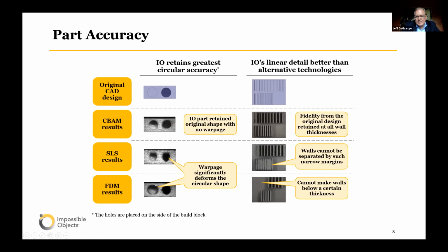Now, bouncing over to the right side here, looking at thin wall features. This is looking at the fidelity of the original design, what kind of retained wall thicknesses can we have? Looking at CBAM, you can see all of those different thickness walls on that coupon and how you can visually see all those. It's more pronounced if you were holding this in your hand. And then you compare that to laser sintering. The smaller wall thicknesses all start to form together if you get really thin features, and then they just don't show up with an extrusion process when you start getting into really thin features. Pretty typical if you conducted this experiment yourself.